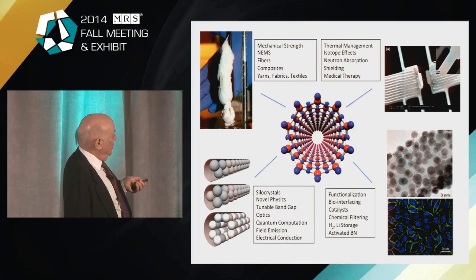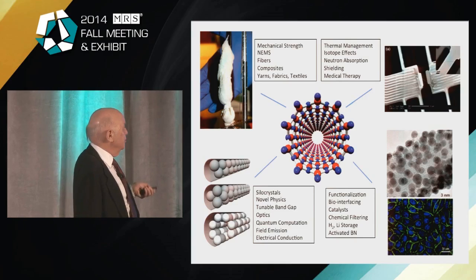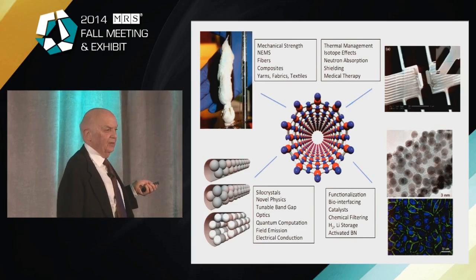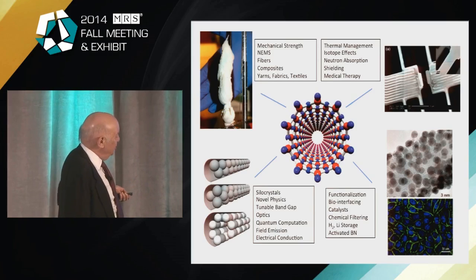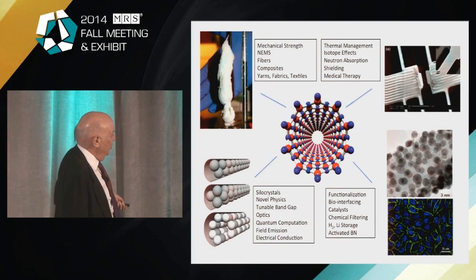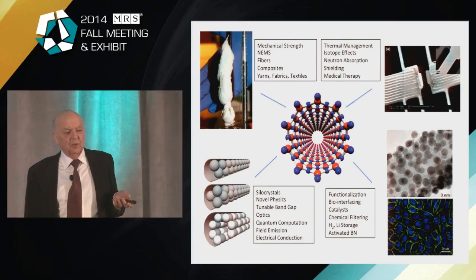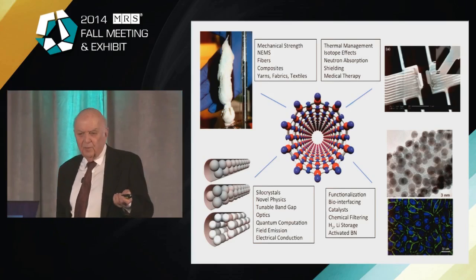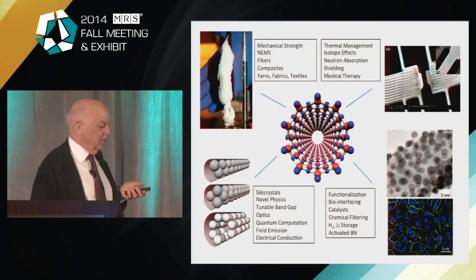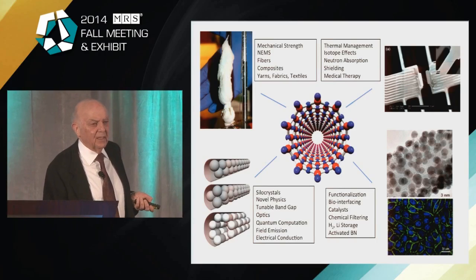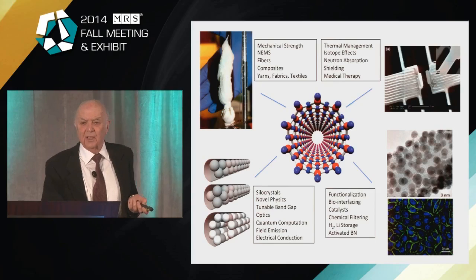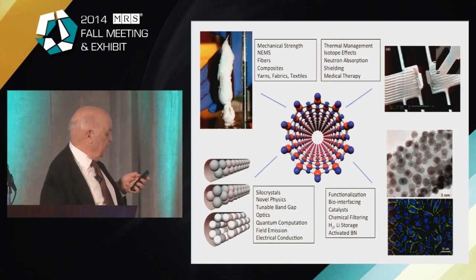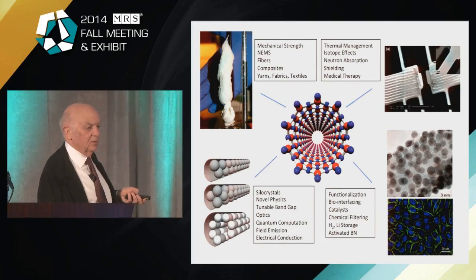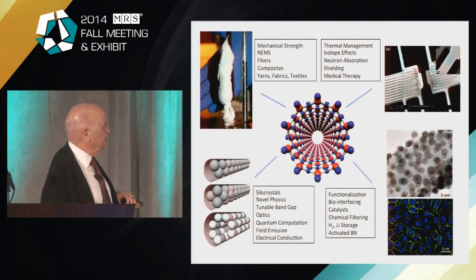When you make yarn out of carbon nanotubes, it's black. It's hard to dye. Boron nitride nanotubes, it's all white. It's called white graphene by some people. You can also put buckyballs, the C60 molecules, down the center of boron nitride nanotubes and do all kinds of things with them. Also, boron nitride nanotubes are more bio-friendly, and they've been used for medical research. And so the big problem up to now has been that it was very hard to make these tubes, and there weren't enough around for everybody. But now there are new methods, and you can make large amounts of boron nitride nanotubes, and there's a significant research program.